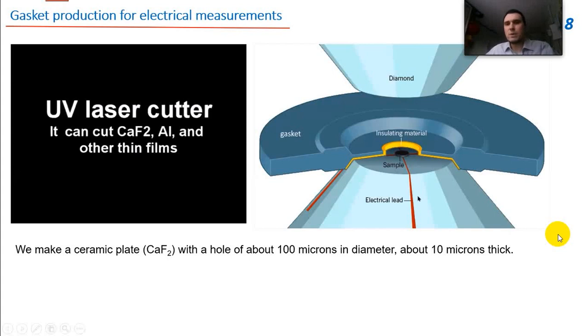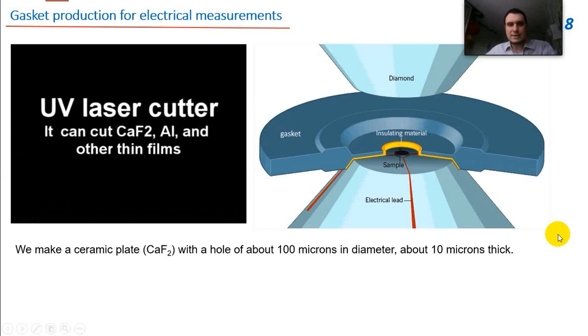Okay, the second step of preparation is to deposit the electrical leads, the electrodes, on the diamonds, and prepare the high pressure chamber where we can place a sample and a hydrogen pressure transmitting medium, or a hydrogen-rich compound as a precursor, such as ammonia borane, NH3BH3, and after that synthesize from these materials the hydride that we need. Okay, the next procedure is cutting the gasket.